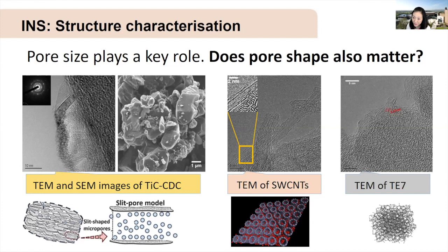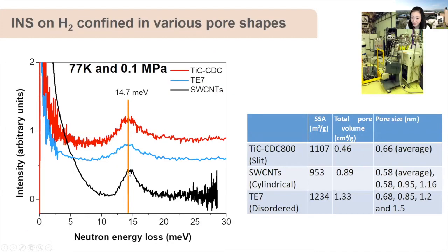To answer this question, we selected three carbon structures, with different pore shapes. These are graphitic layers, which we can see from TEM images represent slit pores, and the single-wall carbon nanotubes representing cylindrical pores. And this is a TE7 carbon. This is a kind of benchmark for our study, a reference control material that has a completely disordered structure. And we carried out this INS experiment on hydrogen confined in the three pore shapes at a different instrument at ILL.